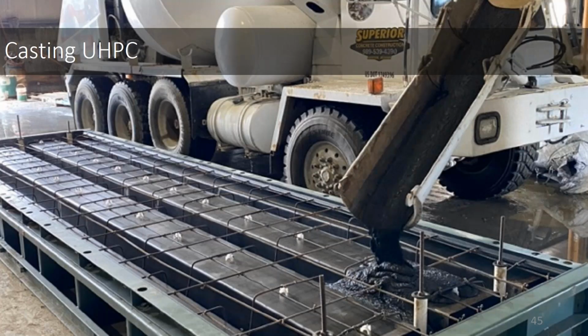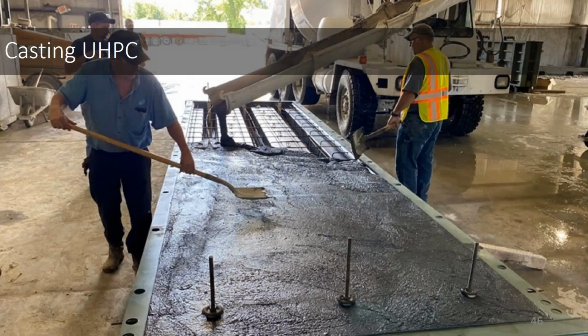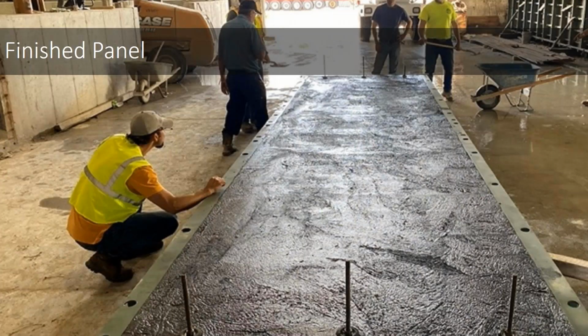So here we are at the plant. We mixed all materials outside and then just pulled right in the door and cast the panels. It is running out just like normal. After day one, we learned a lot. The first panel we cast, the guy said he spent 3 hours pulling the actual panel out of the form. Day two, we tried to pull it out, they spent 3 hours and said we can't do it. So they did some slight modifications to the panel after the first day, and every day after that, the panel came out of the form rather quickly.